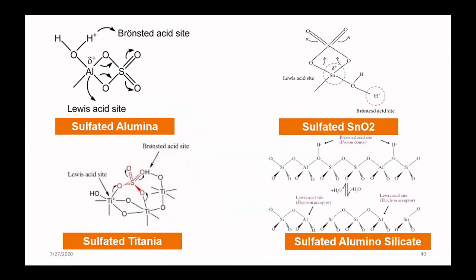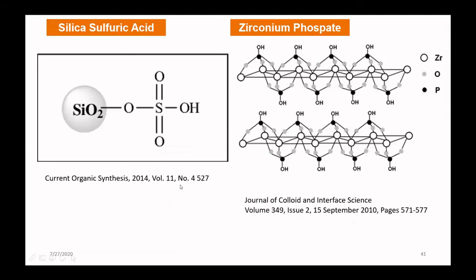This is the proposed structure of sulfated alumina, for example, and sulfated stannate, tin oxide. It has Bronsted acid and Lewis acid sites. And then the sulfated titania, which I use mostly in my research, with Lewis acid sites and Bronsted acid sites. And then sulfated aluminosilicate, for example clay, smectite, zeolite, etc. Silica sulfuric acid, in the literature we found acidified silica, sulfated acids. This also provides a proton. It is very important for acid processes.